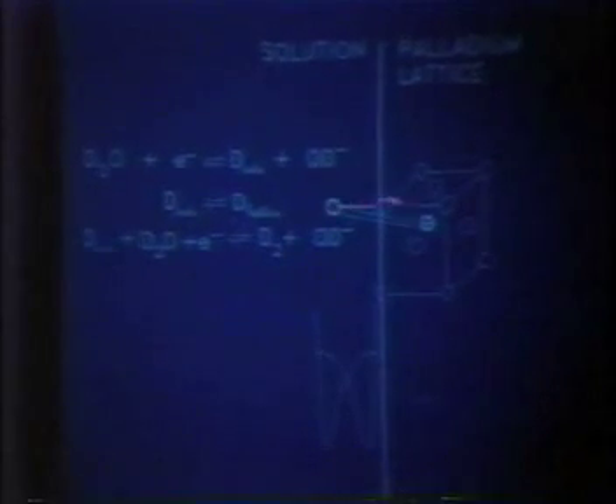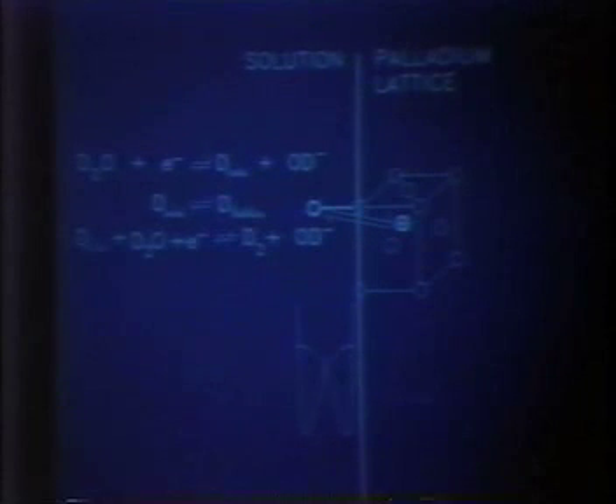Upon adsorption then, it is well known that the atoms then diffuse into the metal lattice, but not as atoms, but as deuterons. So if we can draw a potential energy surface here for the dissociation of water into adsorbed deuterium atoms, we see then that these atoms on the surface then diffuse into the metal lattice and will do so at the diffusion coefficient I just mentioned.